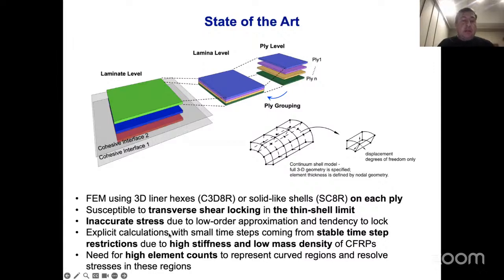In explicit calculations, which are often done for impact events, you get small time step sizes coming from stable time step restrictions because of high stiffness and low mass. And also, when you start looking at curved structures, you need high element count just to represent the curved geometry and resolve the stresses in these regions.